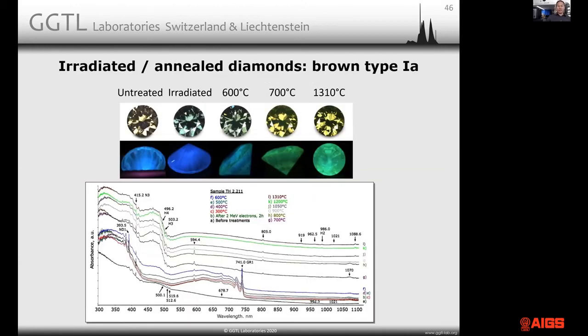Let's have a look at what happens when you irradiate a brown diamond. There are a lot of brown diamonds out there, and the market was not always very favorable to them, which seems to really be changing in current years. But quite a few of the lighter brown colors, when the color is not distinct, were irradiated. So you can create what's shown in this slide. You can take a light brown diamond, irradiate it, and it turns greenish blue. Depending on the radiation dose and energy, you create either a more blue or a more green color. And then you can heat treat them. Depending on what your stone originally looked like and how your irradiation was, you might induce a pretty yellow hue into your sample. That's one way of doing it.